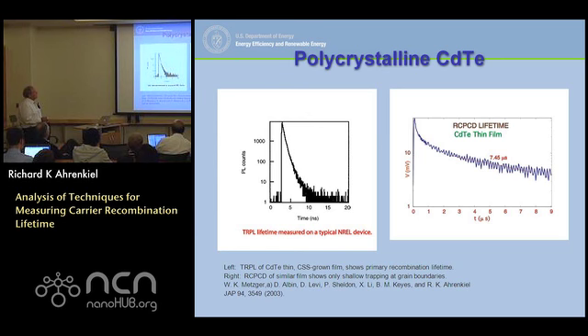In PCD, on the other hand, we don't have the time resolution to see the primary response, but we see this long decay here. This is the trap-mediated decay. This is the electrons in shallow traps at grain boundaries that are being thermally emitted, so they're emitting electrons for a long time after the primary pulse. And this has nothing to do with the recombination event. It's just a shallow trap event, and it's an artifact. So separating artifacts from real recombination is one of the challenges that we're always dealing with.